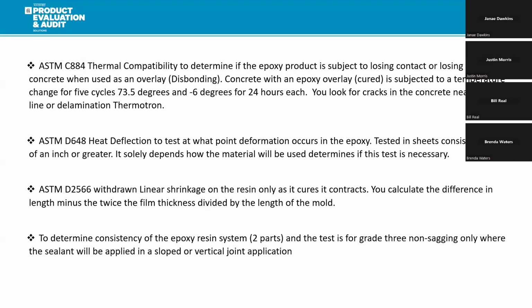Also ASTM D2566, which is withdrawn. It's a linear shrinkage test on the resin only. As it cures, it contracts. So you want to calculate the difference in the length minus twice the film thickness, divided by the length of the mold. And like I said, a lot of DOTs don't do this. They refer to third-party labs to do this test because of the cost or how time-consuming it is.